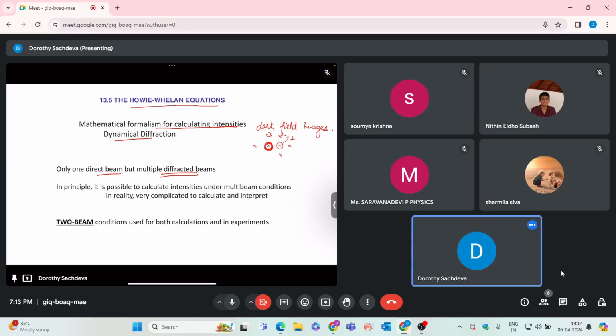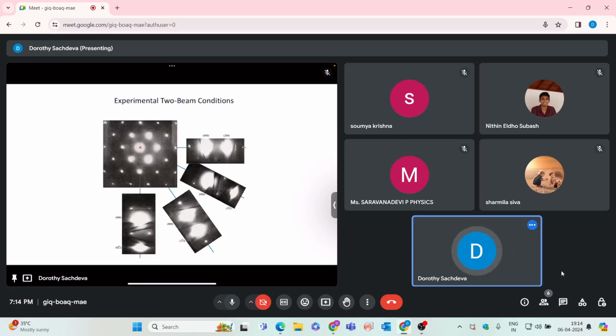So two beam conditions, is it possible to calculate? There is one two beam condition where you can do the imaging of your defects majorly. Suppose this is your direct spot and this is your diffracted spot, then you will move your sample in such a way that your diffracted spot comes in the center. Earlier your Kikuchi lines were like this and your aim was to align or tilt the specimen in such a way that you are in the exact zone axis condition, that means at the exact center of these Kikuchi lines.